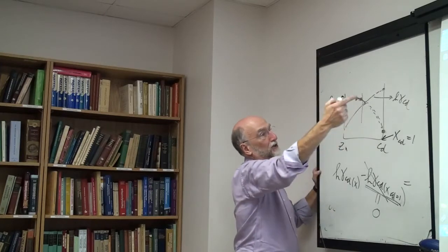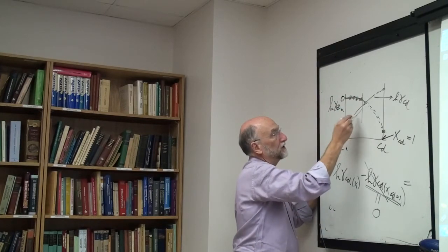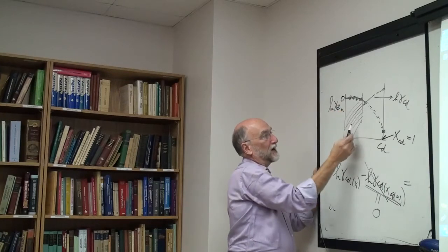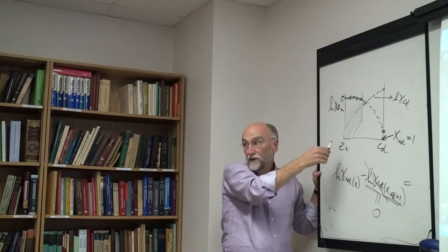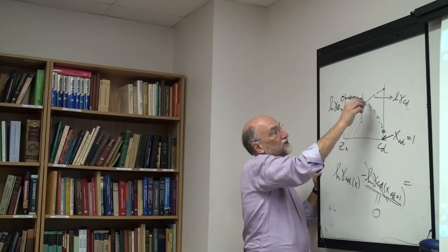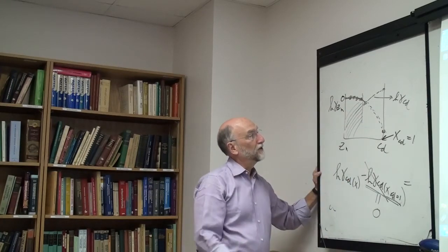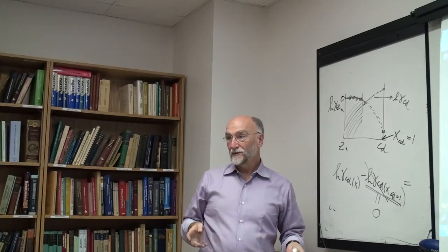So the solution of the differential equation is a family of curves. For log gamma cadmium, a family of parallel curves over here, which differ by the constant of integration. Only if you're sure that this extrapolates all the way to here correctly are you going to get the right curve over here. Otherwise, you could get a different curve. Is that clear?